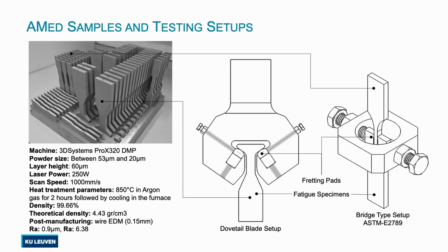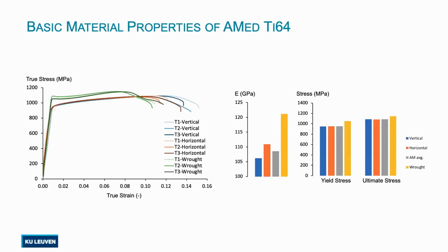We also did the heat treatment. We used 2 different setups here. You see the dovetail blade setup and also the bridge type setup, which follows some recommendations by the ASTM standard. Today, I'll not talk about this because of the time limitation. I will focus only on, as I call it, the semi-component level testing. So some basic material properties before we start doing fretting fatigue tests. We wanted to know that the material is strong enough, at least comparable with the data that we have. We see that it's very typical behavior, so more elongation, less tensile stress and ultimate stress, and also the modulus of elasticity is lower than the wrought material here.